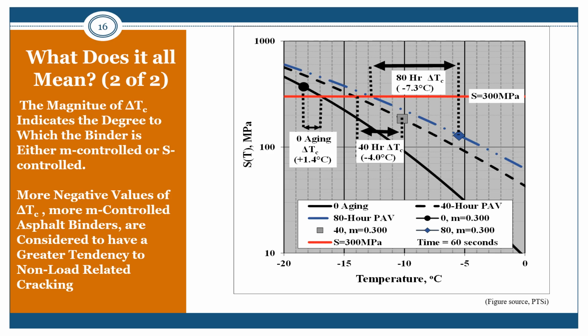It's what will be used probably in the specification parameters. Research has indicated that more negative values of delta Tc appear to be strongly correlated to non-load related cracking and other distress related to poor relaxation properties. A delta Tc specification warning limit of minus 2.5 degrees C at 20 hours PAV aging and a failure limit of minus 5 degrees C at 20-hour PAV aging has been suggested for consideration as potential specification criteria.